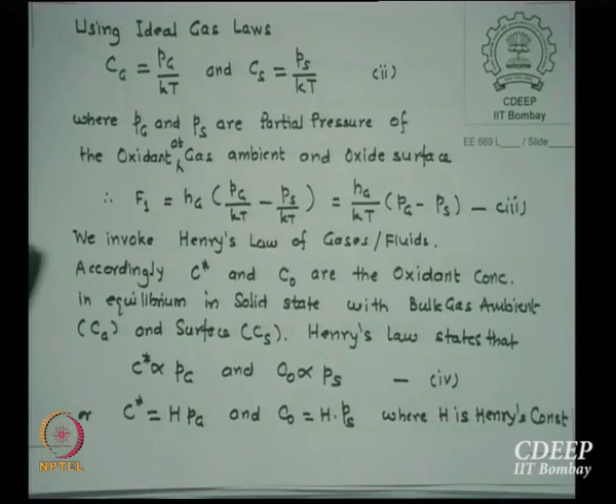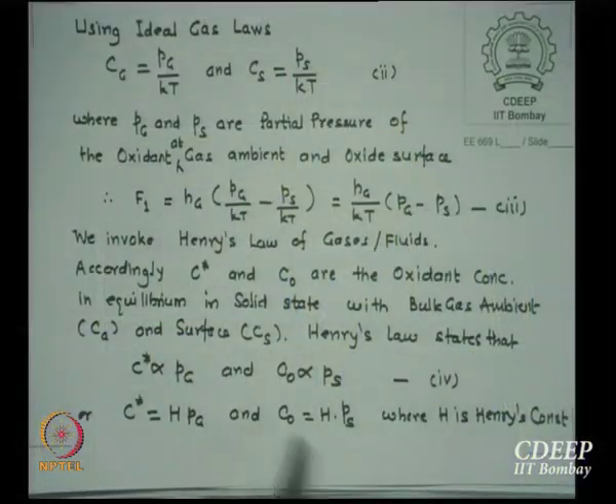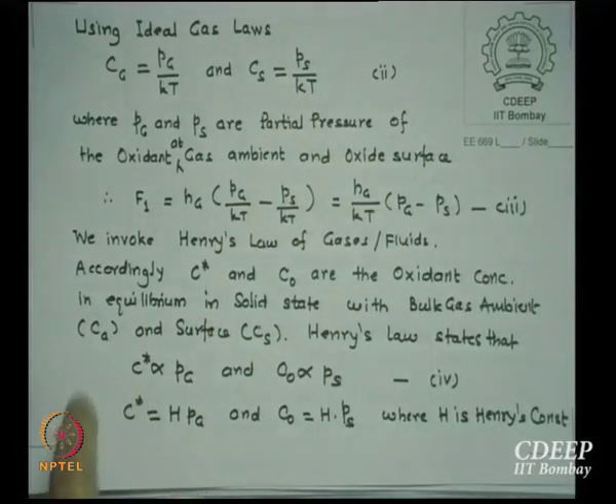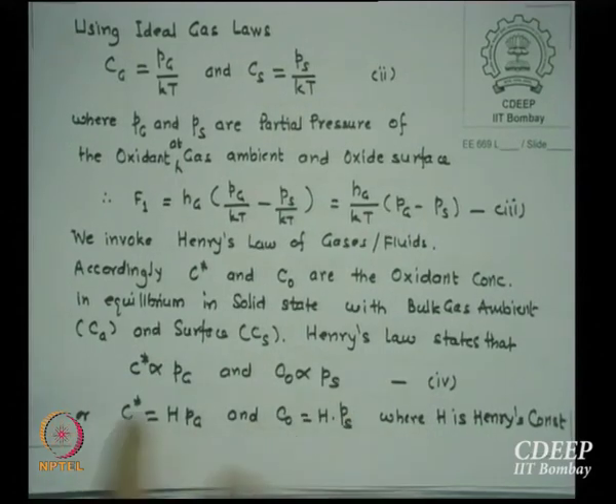What is the method? First I converted Cg and Cs into equivalent partial pressures. The partial pressures are related to their equivalent solid state concentrations by using Henry's law, where H is Henry's constant. So now I have C star and C0, which are at the surface of SiO2, in solid phase. Please remember, that is the oxidant we are going to diffuse through. I repeat, first we related Cg and Cs to Pg and Ps, and then we wrote this equation. Then invoking Henry's law for fluids, C star is proportional to Pg, C0 is proportional to Ps, so C star is H times Pg and C0 is H times Ps, where H is capital H. And now I substitute Pg and Ps from here into equation 3.